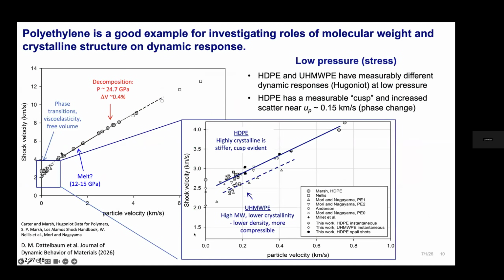So we performed a number of shock experiments on those two different types of polyethylenes, and I show that on the left-hand side overlapped with the Marsh data from the Marsh compendium. And what I want to show you is just that if you zoom in on this low pressure regime, there looks like what could be a lot of scatter in the data.